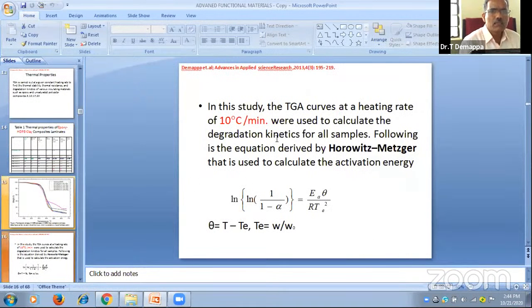Then for the kinetic study, thermogravimetric analysis in the previous figure or graph, the heating rate was 10 degrees centigrade per minute. We calculate the degradation kinetics, IDT for 5% weight loss and 10% weight loss. The energy of activation and order of the reaction were calculated by the Horowitz-Metzger equation. This is the equation used to calculate the energy of activation and order of the reaction itself.